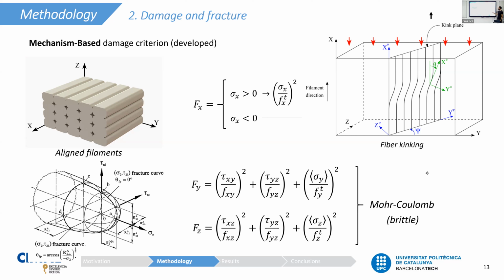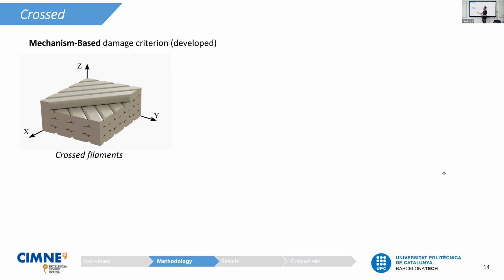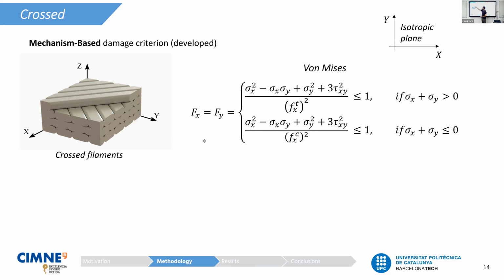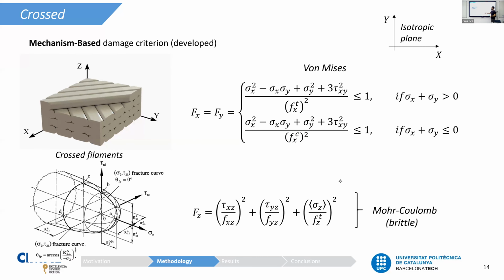And the same process applies for the crossed filaments. In this case, in these crossed filaments that are stacked in the XY plane, the Z direction is the one where the decohesion occurs. Therefore, there's a brittle failure, and therefore in the Z direction we use the Mohr-Coulomb criterion. For the X and Y direction, since it is an isotropic plane, we use a von Mises criterion.